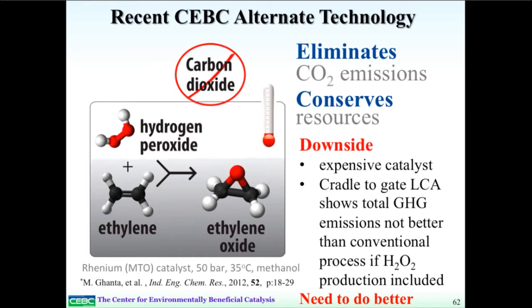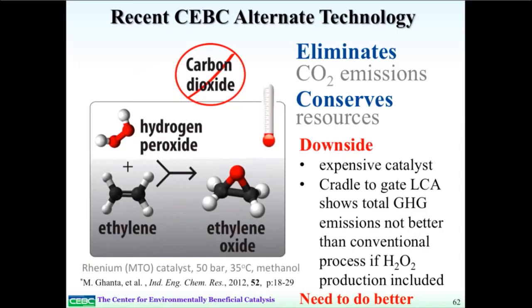So what we first started trying to do at the CBC was to develop an alternative technology to the original silver catalyzed system. And here we're looking at the epoxidation of ethylene. In the silver catalyzed system, oxygen is used as the oxidant. One of the problems there is you're working at relatively high temperatures. You've got mixtures of ethylene and oxygen in the system, and so you have severe safety concerns. One of the things we're trying to do in the CBC is lower those safety concerns by performing this in the liquid phase. And one aspect of the CBC that's been a major theme since its founding is the use